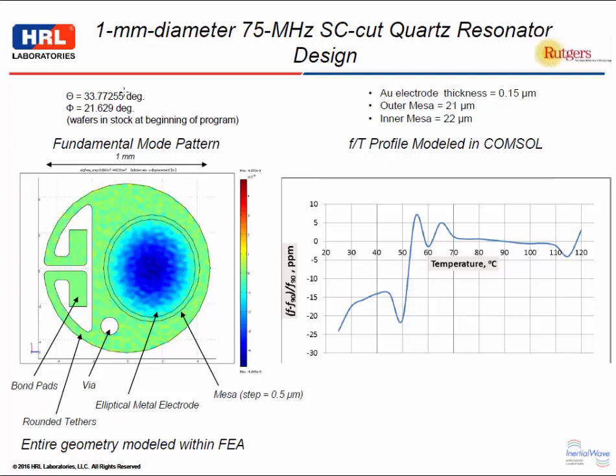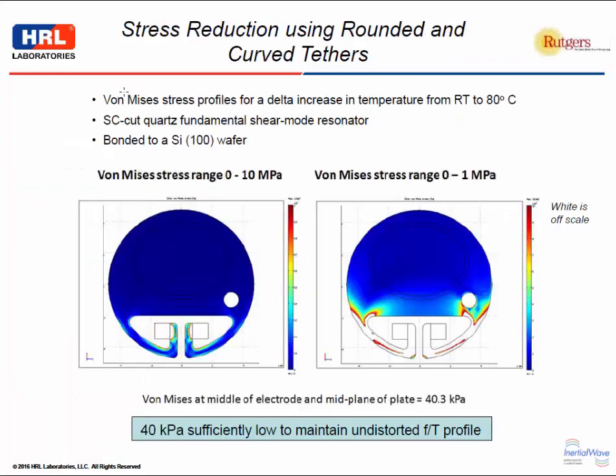We did add these sort of unique rounded tethers. These are the bond regions to isolate the device from stress. And stress is always an important factor when you're integrating these quartz devices on silicon to maintain a low stress in the active region. This shows our stress calculations that we did on these rounded and curved tethers. This is taking a bonded device that's solidly bonded to 100 silicon, from room temperature up to 80 degrees. And you can see the tethers are doing their job.